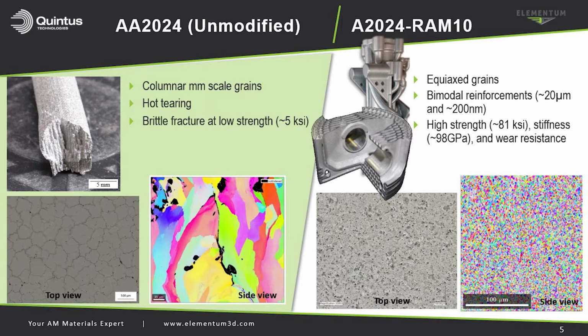Very interesting. And for a little clarification, is this approach more geared towards innovative new materials for powder bed fusion approaches, or for traditionally manufactured materials with slight tweaks to their existing chemistry? Great question, and it's actually really well suited for both of those things. We can take traditional materials that were designed for other traditional processing, like wrought processing, that may not have great weldability or printability in the laser powder bed fusion type AM processes, and we can modify those alloys with fairly small compositional changes and now make those versions printable with great microstructures where otherwise they would suffer from extensive cracking.